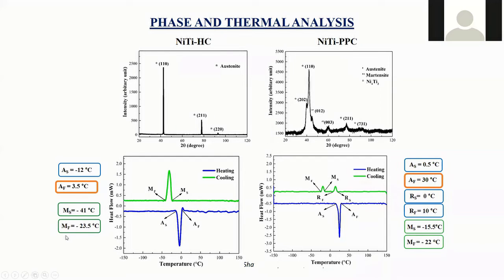Very importantly, what we have seen is that the martensite start and finish temperatures for the solutionized alloy versus the precipitated alloy are distinctly different. And even more important than that is that the austenite start and finish temperature in the case where we do not have the precipitate, the austenite finish temperature is only 3 degrees centigrade. So this means that the material is in completely austenite form at room temperature.